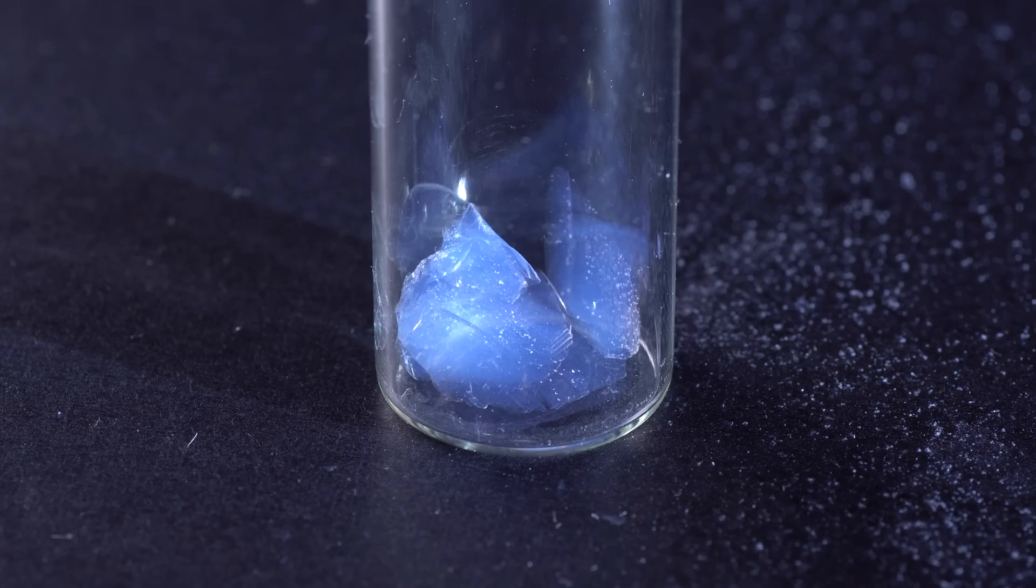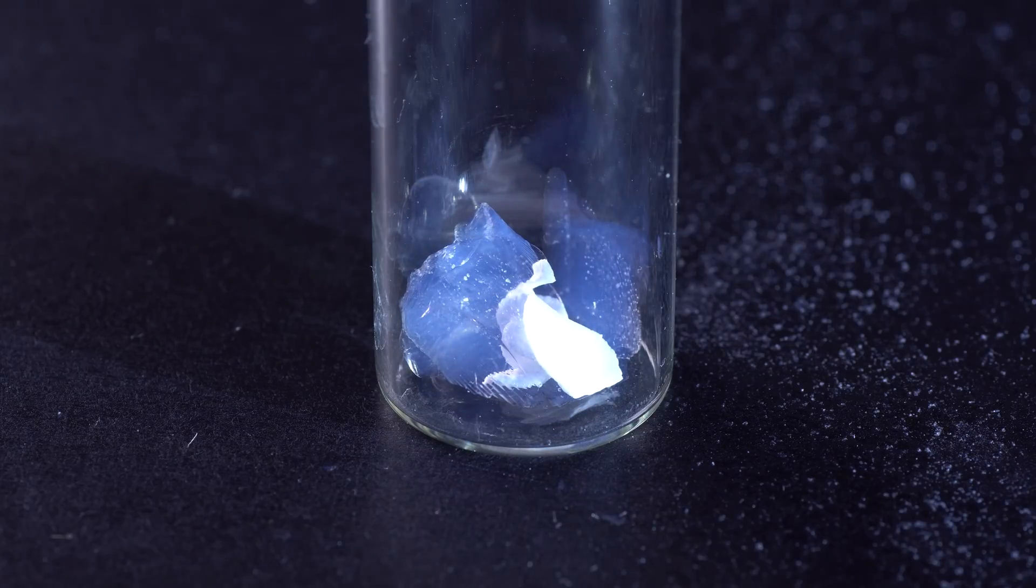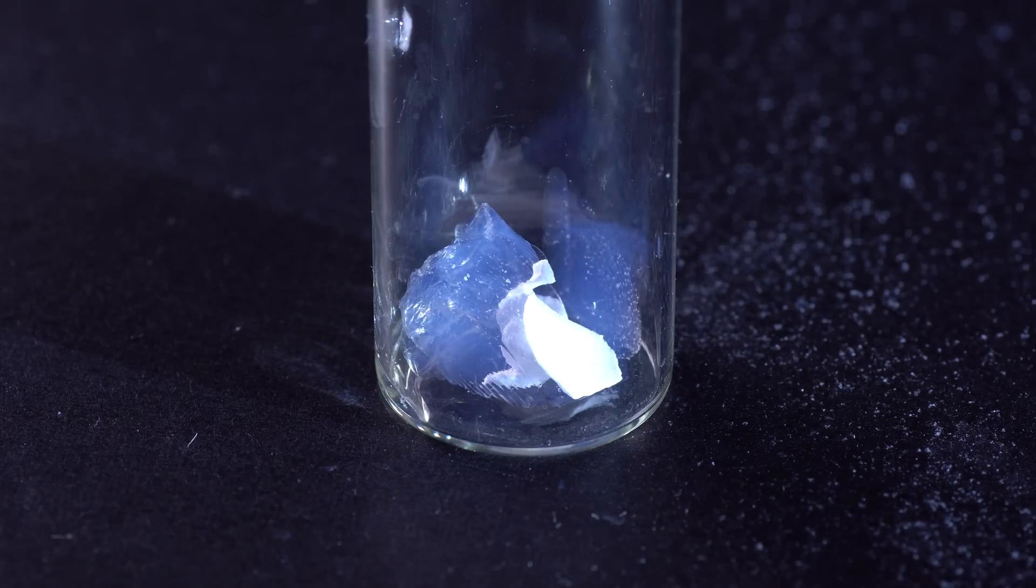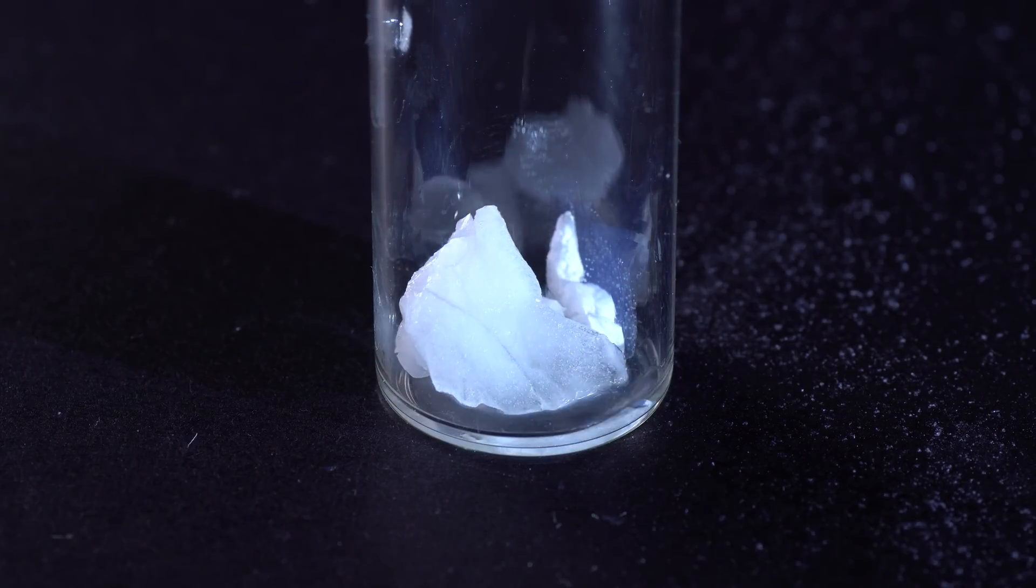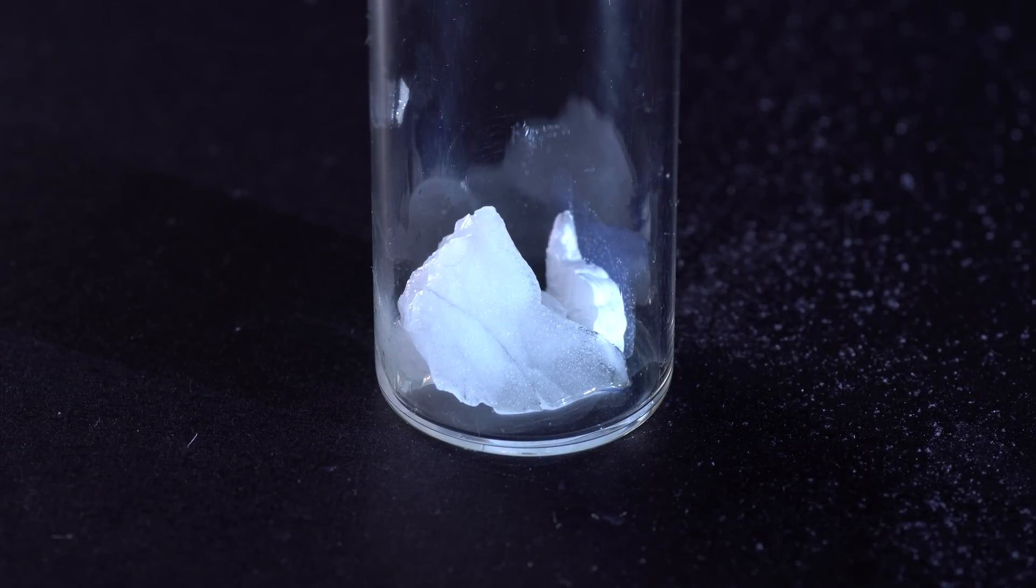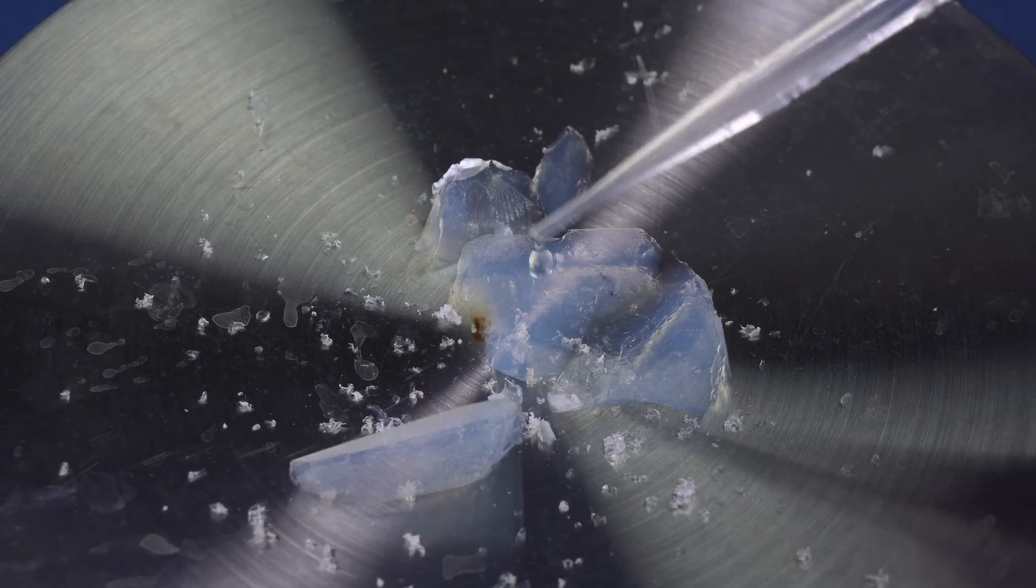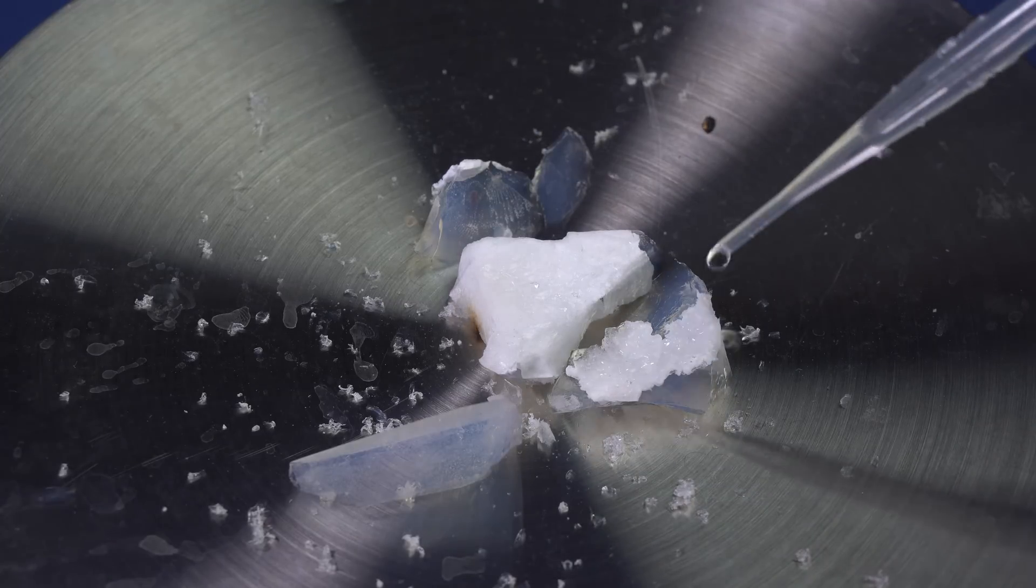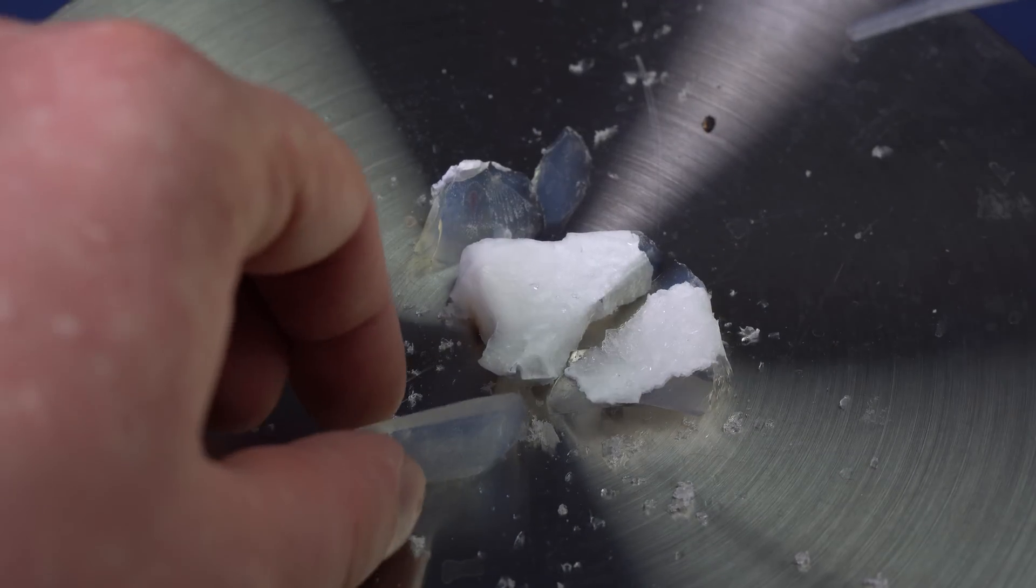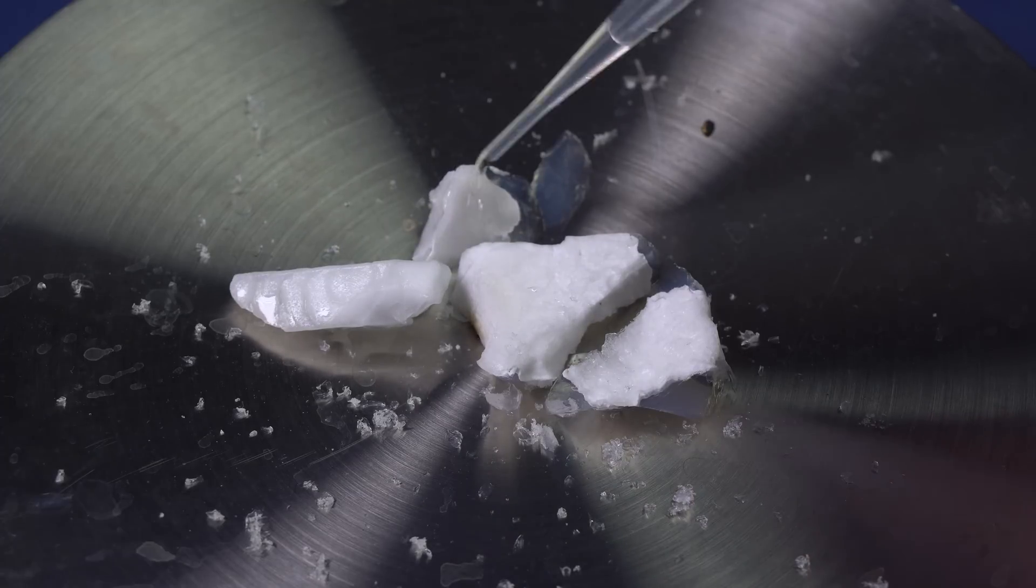The main problem with aerogel, especially with silica aerogel, however, is the fact that it is hydrophilic because this material has hydroxyl groups on its surface. When it comes into contact with water, aerogel soaks up the liquid and turns into a whitish surface, similar to colloidal silica. Thus, if water is spilled on aerogel, it will immediately lose its unique properties and will turn into quite expensive rubbish.